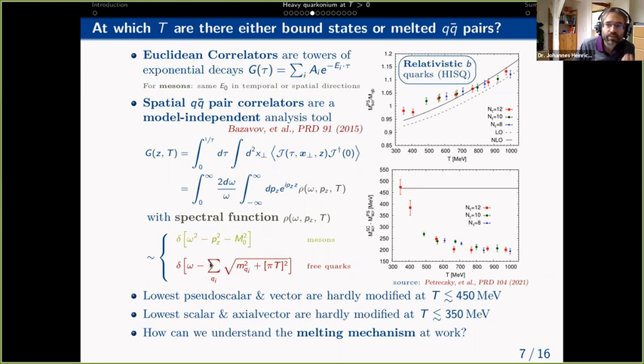On the other hand, if this meson has already been melted, then we'll have a dependence on the square root of the squared pole mass of the valence quarks and a pi T squared factor under the square root. If this mass were very small, it would be linear in T, but if we consider large mass quarks, we have something that looks rather like this square root term over here.